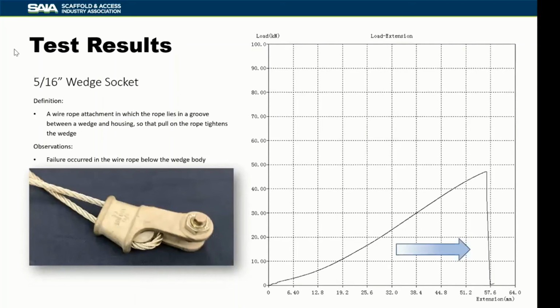Now the 5/16-inch wedge socket. If we look at the socket that is properly sized for the type of wire rope we're using, the breaking force is a little lower than with some of the other termination types, and the elongation is significantly higher. That's attributed to the way the wedge socket works: you truly have to drive the wedge into the socket. That allows some slippage in the wire rope, as well as more elongation or extension because the wedge has to drive into the housing.